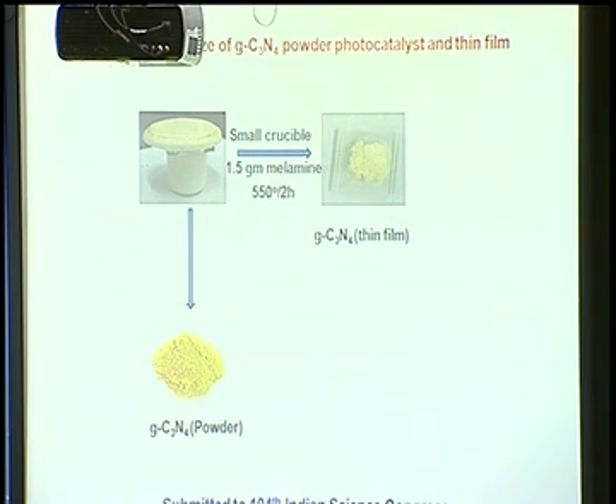This is one-step synthesis of graphite carbon nitride powder photocatalyst and thin film. Actually, most of the work that I have reported is on graphite carbon nitride as a powder photocatalyst, but it is very difficult to synthesize the thin film, because its conductivity is very low. So here I have adapted a unique technique where I can synthesize, in one step, the powder photocatalyst as well as the thin film. I have taken melamine, the source containing carbon and nitrogen,